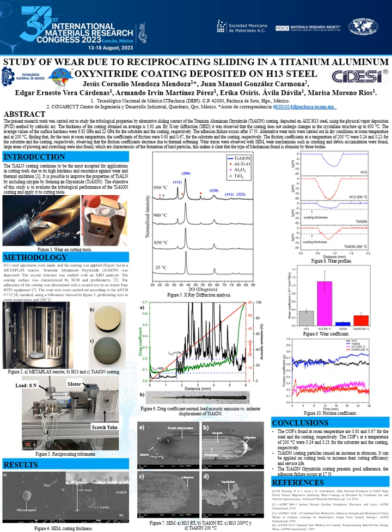Figure 4 shows the thickness of the coating obtained, 6 micrometers. Microdroplets and pores can be observed on the surface of the coating. In the cross section, cavities and microdroplets can be observed. This is typical of PVD coatings. The coating has a columnar structure and will have good mechanical and tribological properties. The hardness of this coating is 22 gigapascals.